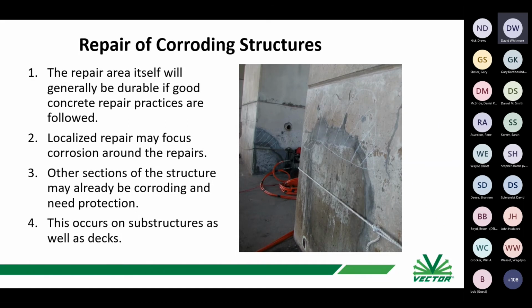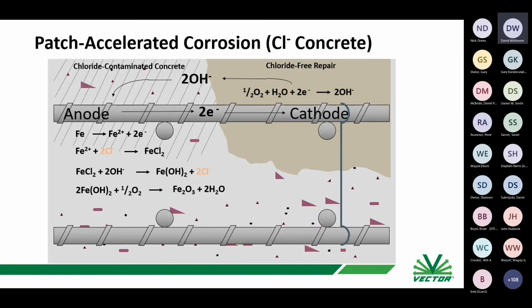This is actually a Florida DOT bridge, and you can see good quality repairs were done on those piers in a marine environment. You can see across the top of both of the repair areas, additional delaminations have been marked out.